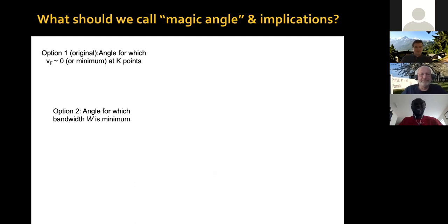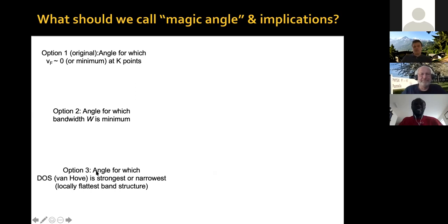And yet another option is the angle for which the density of states, in particular the van Hove singularities associated with the flat bands, is strongest or narrowest. So not the angle for which the whole bandwidth is minimum, but the angle for which locally in the band structure you have the flattest band structure at a given energy, locally in momentum space and energy. This approach has been, for example, suggested by the Columbia group working on STM in magic angle graphene.